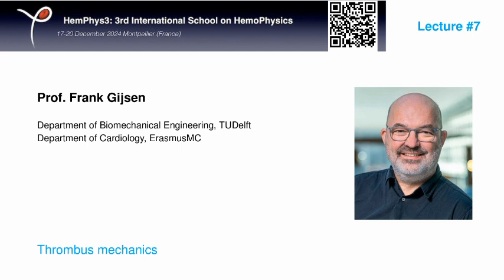I have two quick questions. Regarding the viscoelasticity, do you think that could be important, because after the time relaxation, maybe we can have a strain that is higher than the one predicted by the elastic model? My answer is yes, and even clinicians know that, because once they deploy the stent, they always wait. They don't know how long they have to wait, but they know it takes some time before the retriever is fully engaged with the thrombus, and that is of course a viscoelastic effect.